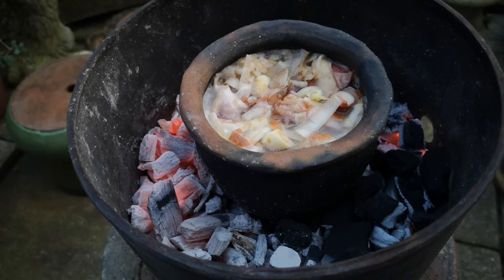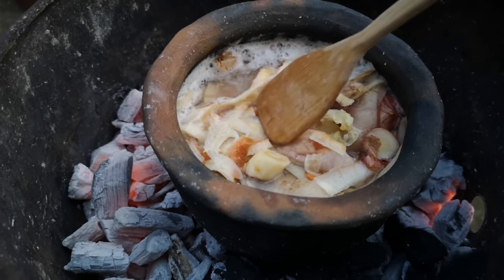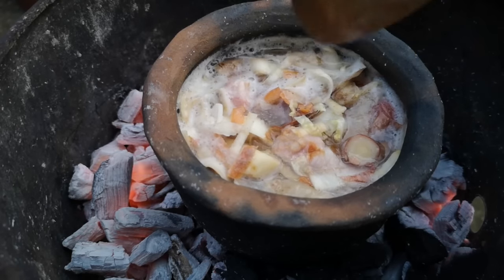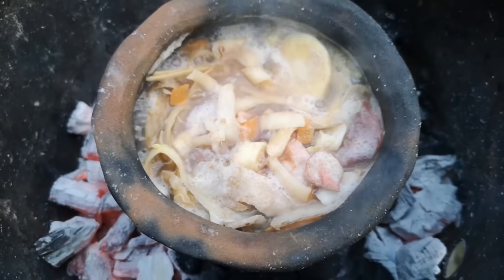This is an unglazed earthenware pot — it's quite porous, but people have been cooking in unglazed earthenware all over the world for millennia. Water soaks into it and would eventually seep through, but not so quickly as to present a problem. The porosity means some of what soaks in will be parts of the food itself, which might sound like a hygiene issue. But for a pot heated every day, that material is more likely to eventually polymerise and carbonise, forming a sort of seasoning that makes the pot more watertight.